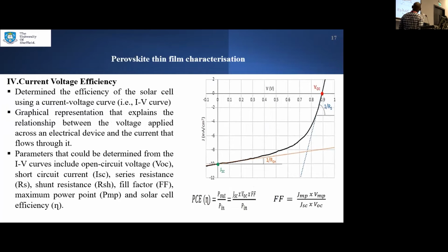And then finally, this is a solar perovskite thin film. This is an IV curve that illustrates how the open circuit voltage is generated using a solar simulator. Actually, this solar simulator gives all the results, because after you have made your solar cell in the laboratory and you use the solar simulator, it gives all the results. But to accurately determine the efficiency of the solar cell, it is also advisable to make the calculation manually.